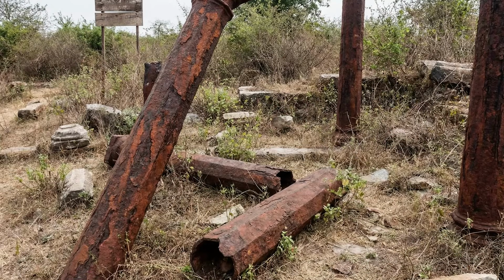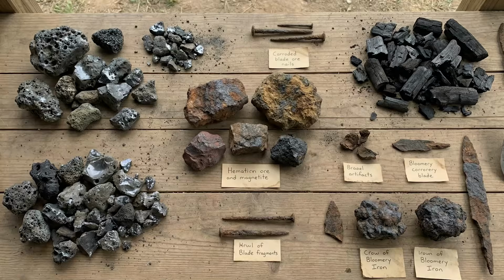Similar iron objects from the same period, even those with comparable phosphorus content, show much more corrosion. The Delhi pillar seems to have benefited from a combination of factors: composition, forging technique, mass, and environment that individually wouldn't be sufficient, but together create exceptional durability.